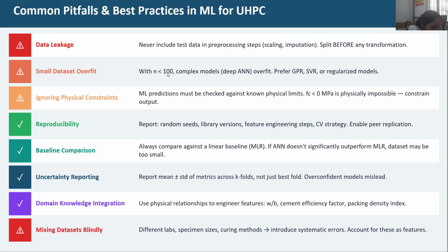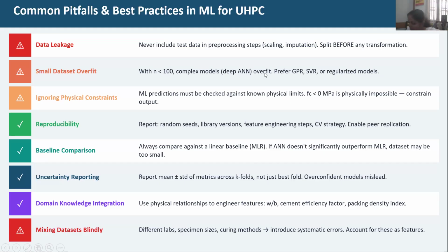And the smaller database, that's again one more thing. When the database size is less than 100, that gives overfitting, which will not give the better results. So when you have the data set less than 100, prefer to go with either GPR, that is Gaussian process regressor, or SVR, support vector regression, or any regularized models. Again, when we report any data with respect to less than 100 or 200 or something like that, the scope of reproducibility will become very minimal. So if you give me the same data and if I perform the same analysis, I might not get the same results as you are getting, or I might not get equivalent results or near to your results. So that's not possible technically.